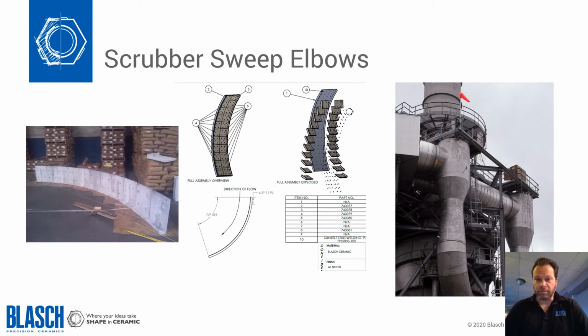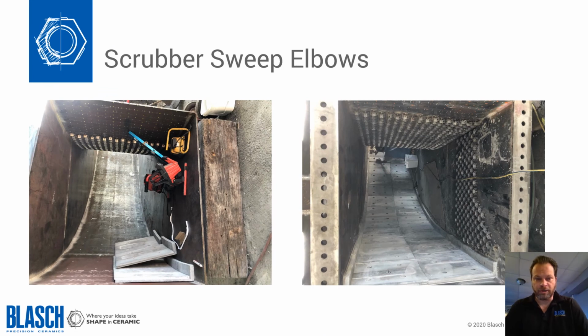At the bottom of the scrubbing tower, this one particular client was seeing some excessive abrasion at the turn or the bend. So Blasch engineers came up with an interlocking tile arrangement that was welded and mortared in place. Pictured here, you can see the before and after installation of these tiles. These happen to be stud welded in 4 locations and were also back filled with some mortar to hold them in place. And then in the upper sections, the upper and left side of the wall and right side of the wall, a hex mesh castable was installed. But most of the abrasion was seen where the tiles were located.